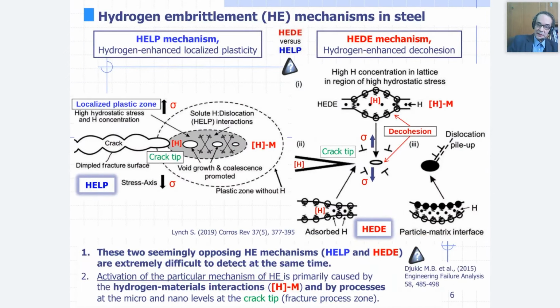Hydrogen embrittlement in steels is still a very hot topic. We have 2 mostly accepted mechanisms presented here. I will talk just briefly about the so-called HELP mechanism, hydrogen enhanced localized plasticity. So, hydrogen enhanced plasticity in the material, not brittleness, according to this mechanism. While contrary, on the other side, we have the HEDE mechanism, hydrogen enhanced decohesion.